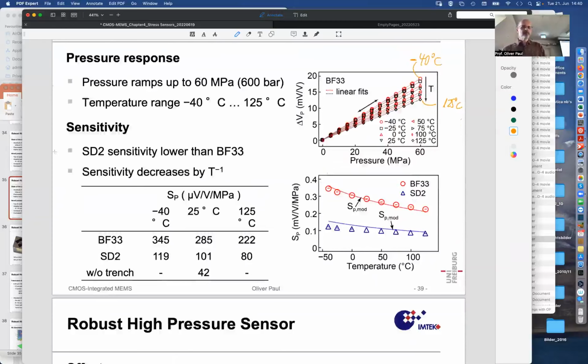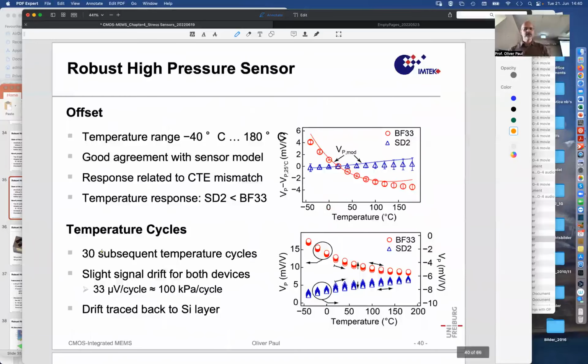Then he found out that this Schott glass has a lower sensitivity than Borofloat. It has other mechanical properties than this softer Borofloat glass. You see the sensitivity here as a function of temperature. And you could also model that using COMSOL modeling. And so Borofloat is definitely the better material, although it likely shows a higher temperature cross sensitivity. And so this is also shown here. The SD2 glass, of course, shows you that, let's say, the output voltage in comparison with the output voltage at 25 degrees varies much more moderately for the SD2 glass than for the Borofloat glass.